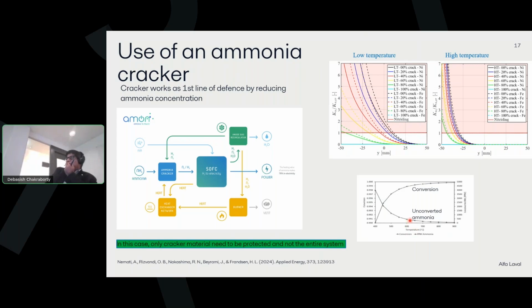And as you can see here, when the temperature in the cracker is around 600, you have very little ammonia left, around 500 ppm, right? So if you could feed the cracker with that kind of heat and then flow ammonia through, then you have very little ammonia left in the stream. This is from this paper by Nemati. And then you can see the nitridation potential decreases as the degree of cracking goes up, right?